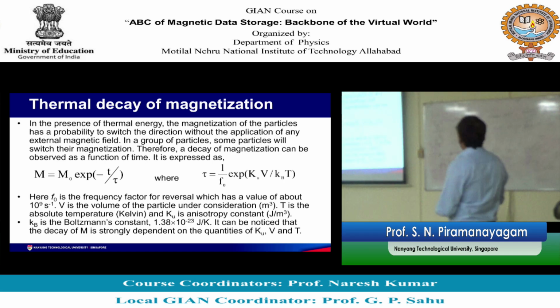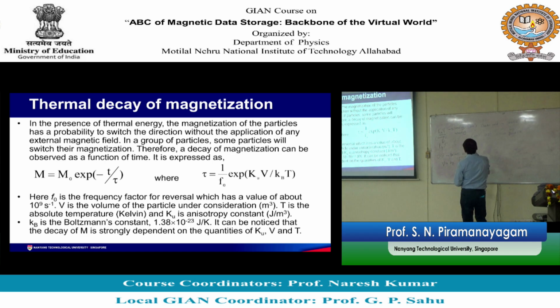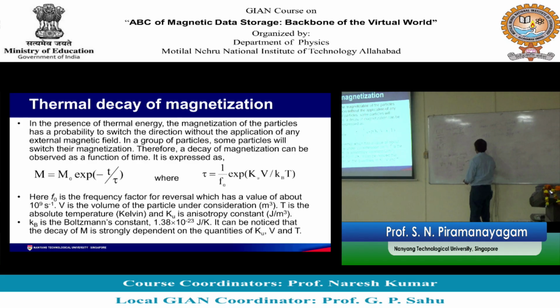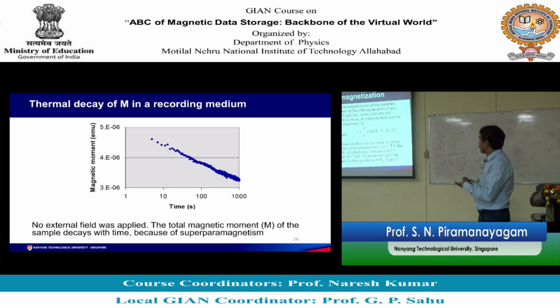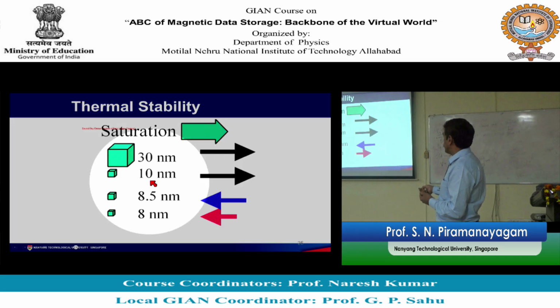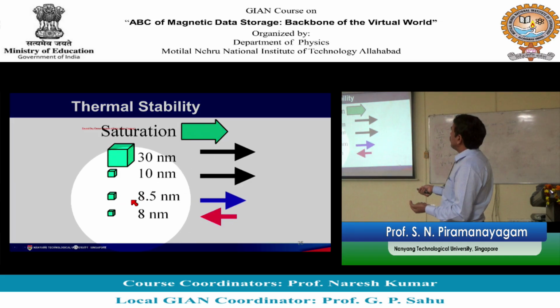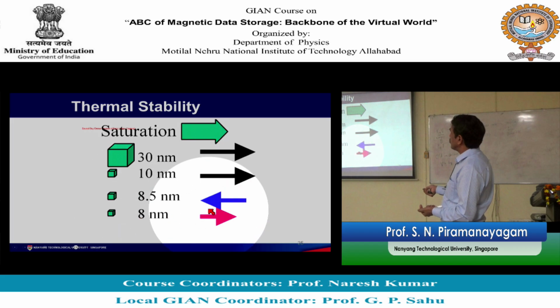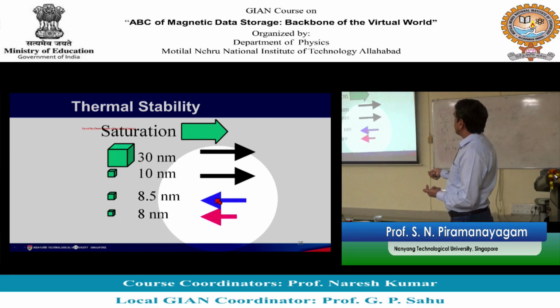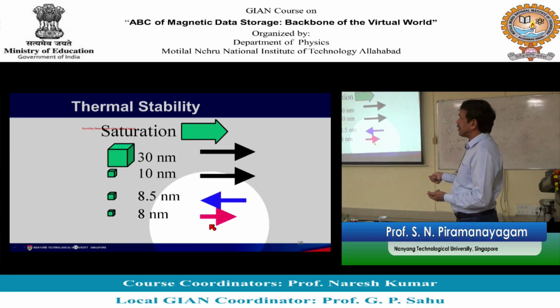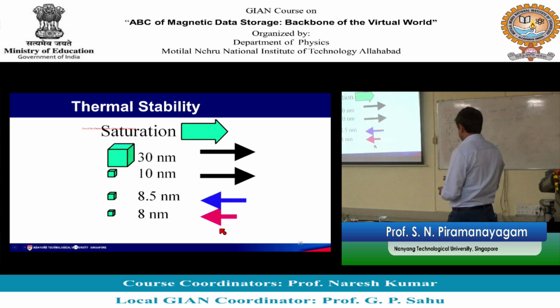But when you shrink the grain diameter to say 8 nanometer or 9 nanometer and make the thickness 15 nanometer, there is a huge reduction in the volume. Very similar to what I showed you here. See here, between 8.5 and 8 itself there is so much difference, right. This does not fluctuate that rapidly, but the magnetization of this fluctuates very rapidly.